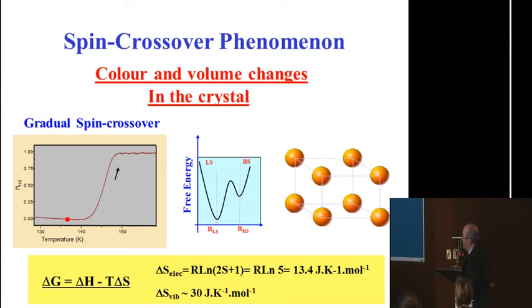So we say that the driving force of the spin crossover is the entropy. Why is the driving force the entropy? Because when you look at the energy, the free enthalpy of the system, you see that the enthalpy is fixed. The change of entropy between low spin and high spin is fixed too. It's 13.4 in the case of spin 2 here. If you include the vibrations, you have something like 30. So this term is constant. This term is constant.